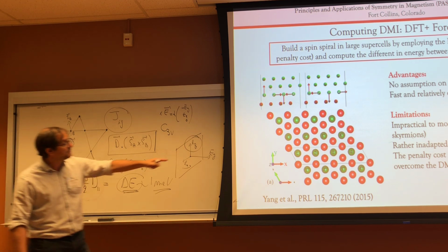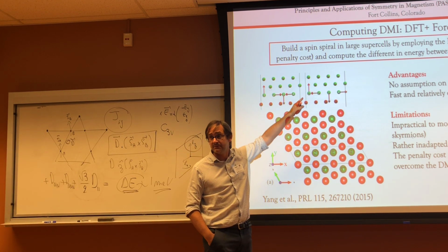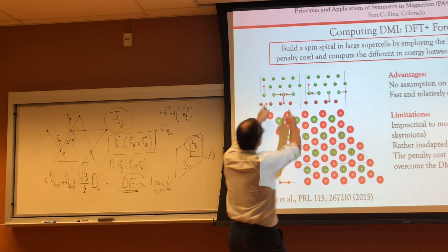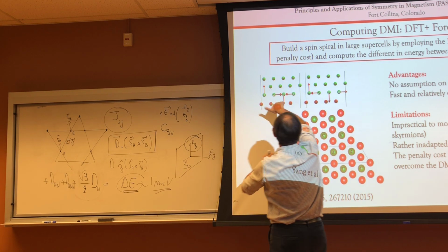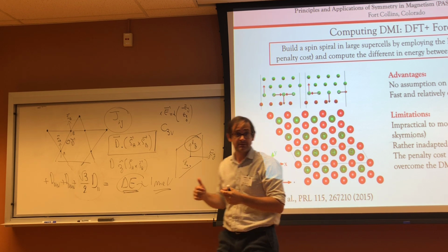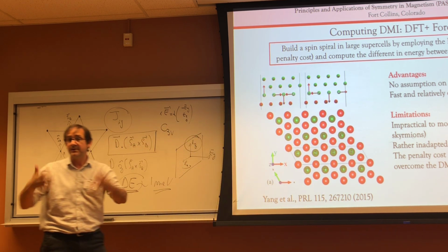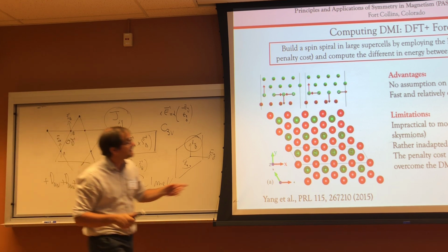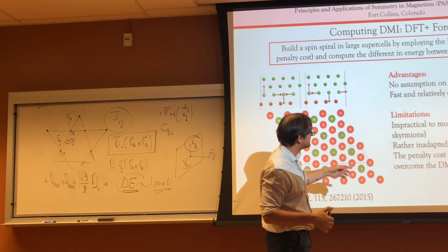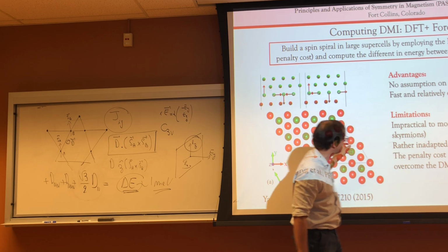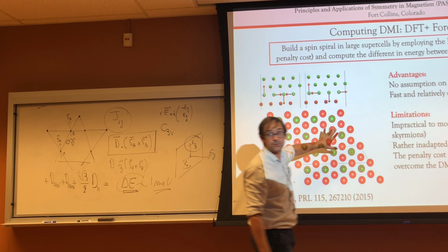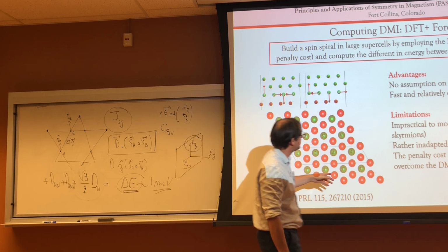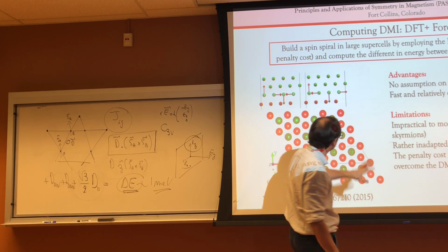But you only have one calculation because you only set one spin spiral. So the only solution you have if you want to be accurate is to increase the unit cell and create smoother spin spirals. And that becomes very, very computationally demanding. So that's the first issue. So that's ill-adapted to metals in my view. It's fine for insulators though, because in insulators it's mostly nearest neighbors. Well, this can be argued, but anyway.